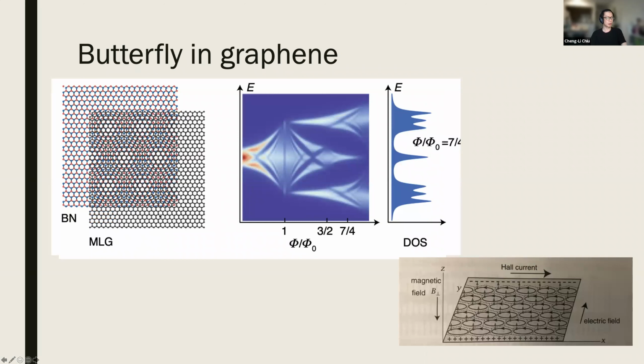What about creating another periodicity using the Moiré pattern? So now if I align the boron nitride and the monolayer graphene, from this image you can see that there's actually a larger periodicity on top of the monolayer graphene and the boron nitride. And this extra periodicity can interfere with the original magnetic field periodicity. It can interact with the previous periodicity.